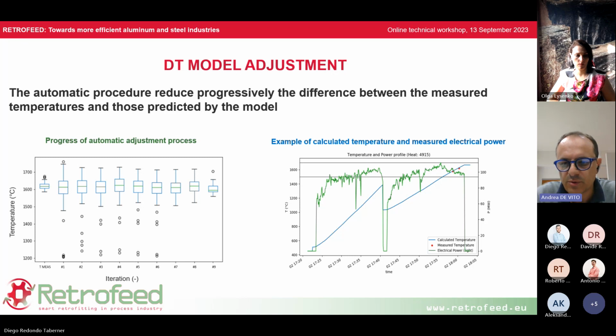On the right graph, it is possible to see the results of the adjustment shown for a typical heat, in which we can see the main input of the model, that is the electrical power, the green line. We can also see the main output of the model, that is the average bath temperature, the average temperature of the steel within the furnace. In this case the predicted value of the model, the blue line, fits quite well the measured temperature, the red points, and also the trend of the curve.